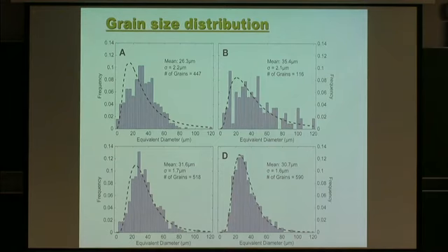You have the same distribution with the normalized grain size? Because if I understood grain size distribution correctly, you have to normalize it to a time-independent grain size, which would be the mean, mode, or median grain size. And in that case, the distribution doesn't look necessarily the same as if you're plotting it to an equivalent diameter.